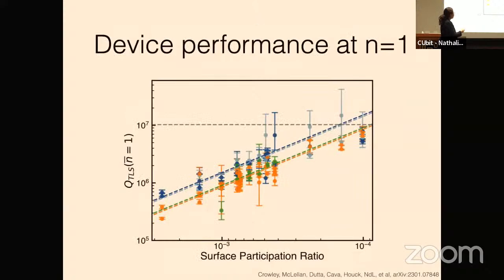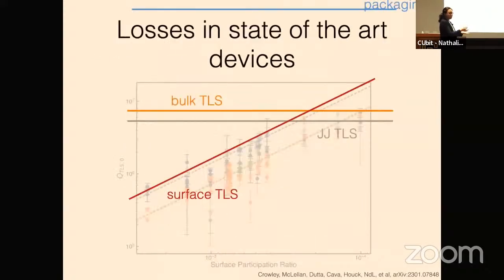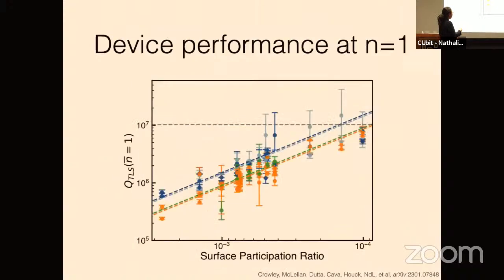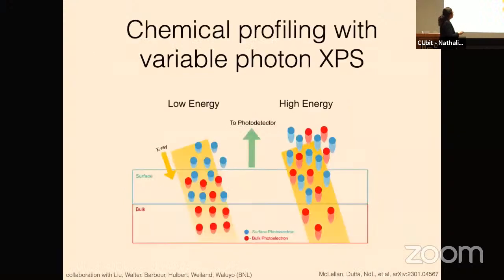Okay, I'll just mention really quickly that everything that I showed here is the linear susceptibility. So it's sort of extracting this QTLS knot, but that's not actually relevant for device performance. Device performance happens at an average intercavity photon number of 1. So what you really want to look at is how good is your Q at this average intercavity photon number of 1, and we get Qs of around 10 million, basically 10 to 12 million in our best devices. Okay, so I promise this will take 3 minutes.